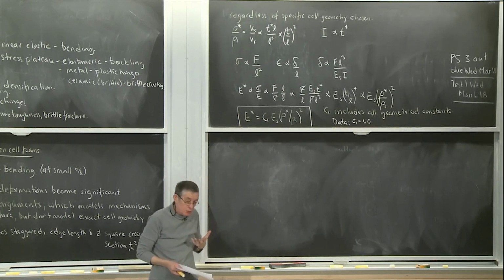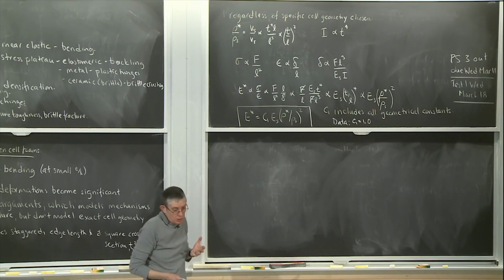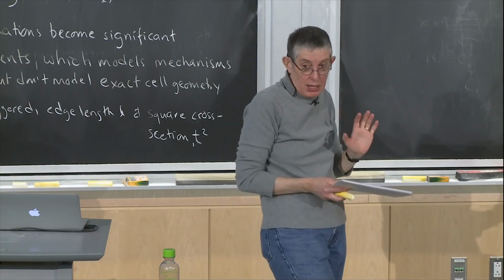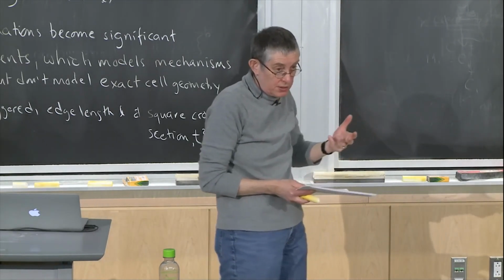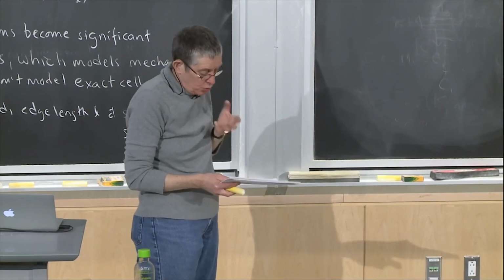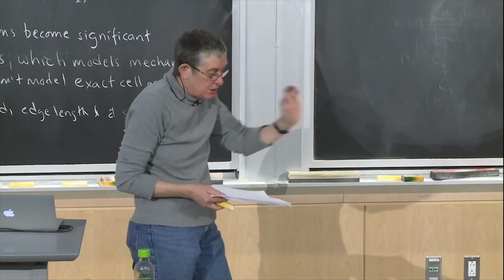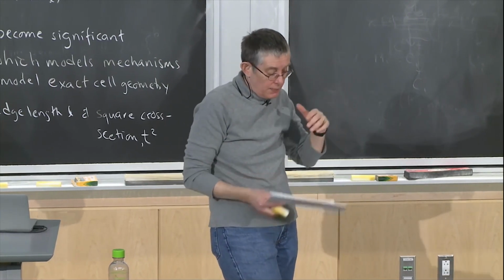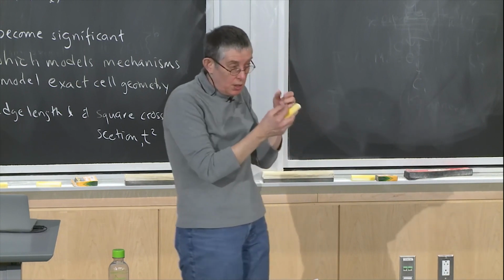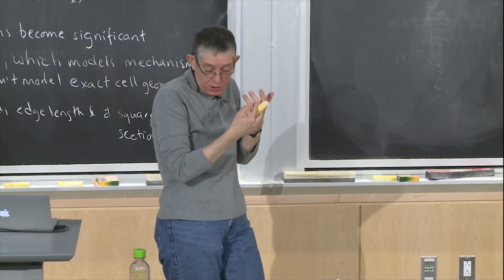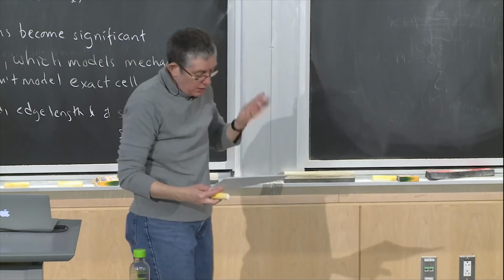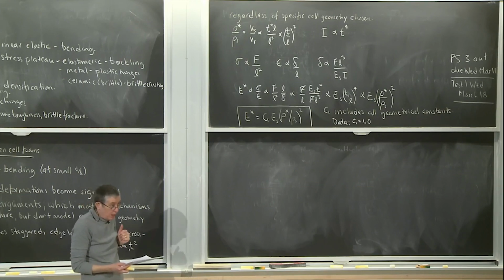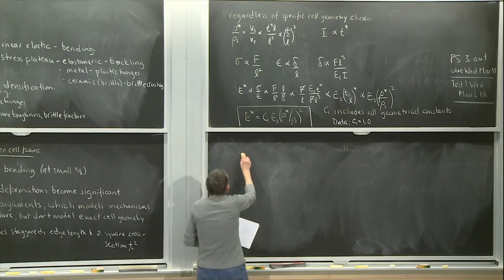And people have also done more sophisticated analyses than this. There's a group of people who looked at doing a full-scale structural analysis of an open-celled tetrakaidecahedral cell. And remember I said they pack to fill space, so you can look at a unit cell. They also made their cells such that the thickness along the length of the cell was not constant. The thickness varied as something called a Plateau border. If you have a foam that's made by surface tension, the edges will tend to have these Plateau borders, and the thickness will vary along the length of the edge. So when they did this whole complicated thing, they could calculate a value for C1, and they calculated 0.98. So it's very close to 1.